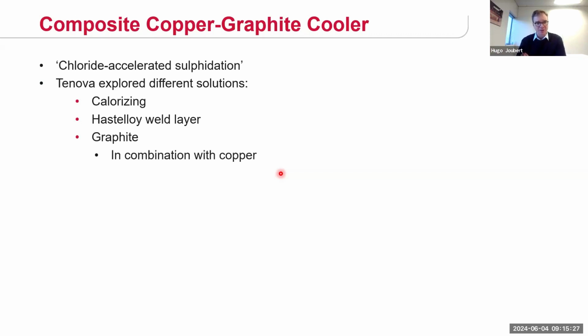So we decided to go for the option of using graphite. We actually have a patent dating from 2006, covering the use of graphite combined with copper, specifically for this issue. In short, your copper keeps the graphite cool enough so it doesn't oxidize, and in turn, your graphite protects the copper from sulfidation, basically prevents the sulfur from getting to the copper.